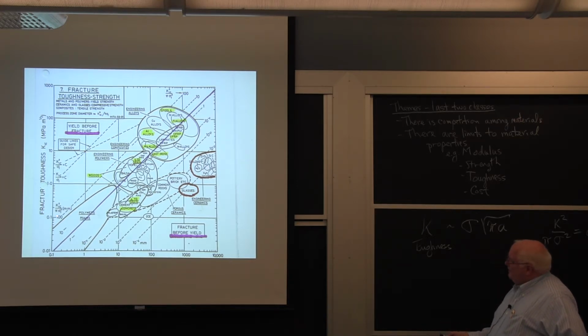But these, the critical flaw size, if you calculate with this formula, which Griffith gave us in 1925, you find out for typical toughnesses here of 100 megapascals meters to the 1/2, interesting units, but nonetheless, it comes out of this. It's the only way you can cancel units on both sides of that equation. You find that steels might have 100 megapascals root meter. Steels are near the top of this in terms of toughness.